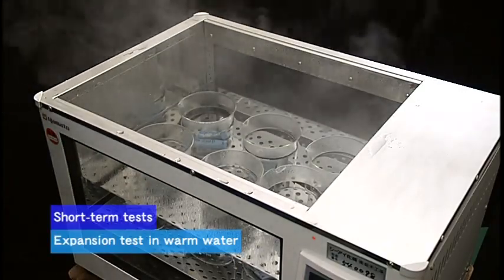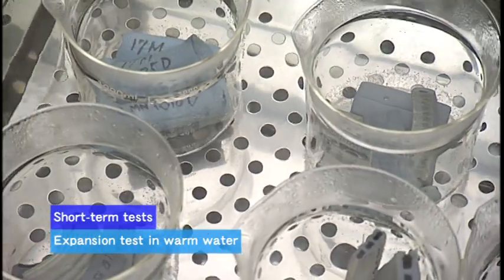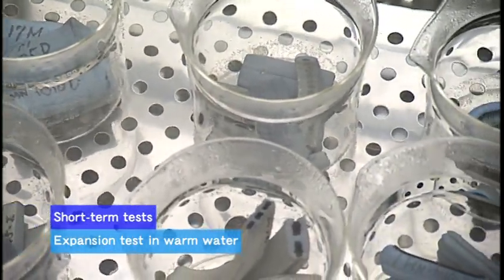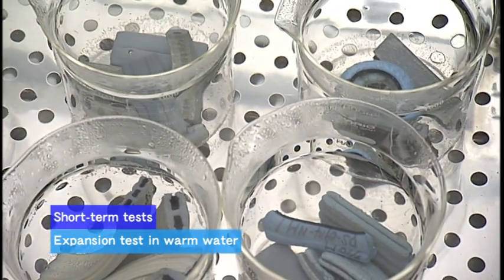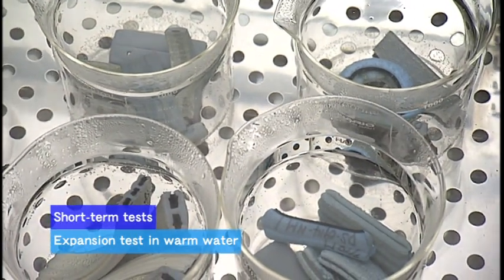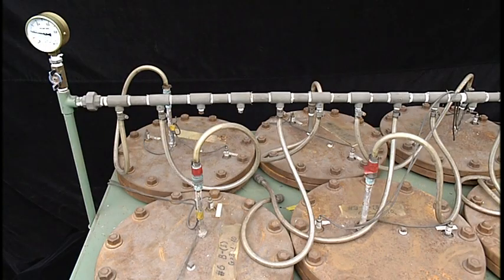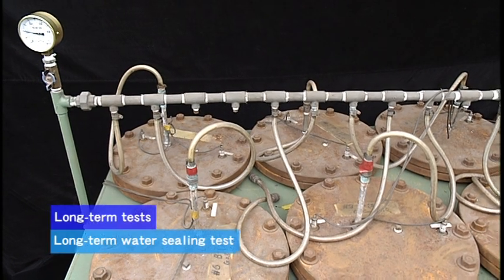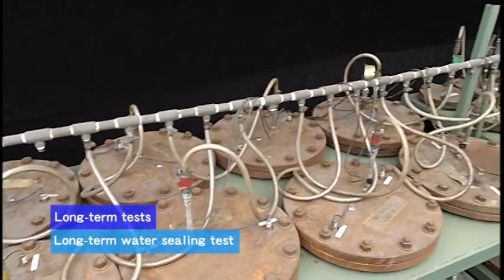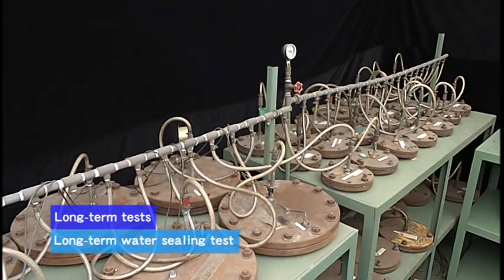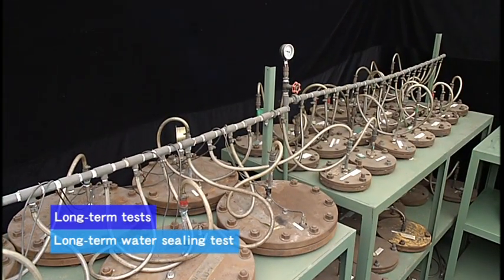This is an accelerated deterioration test done in warm water. It is useful for confirming the durability of Hydrotite water expansion performance in the short term. Test pieces that have completed the short-term expansion tests move on to the long-term tests so that we can further examine their water pressure performance.